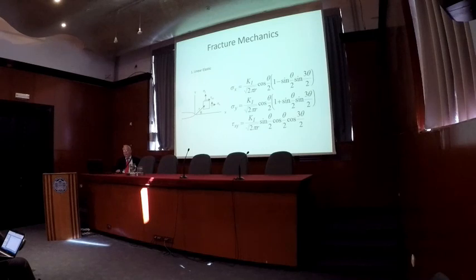The important thing about these is that the distributional terms, where R is the distance from the crack tip to the stress element point, and theta is the angle from the horizontal, are unique. That is, whenever there is a mode one loading, those terms always come up, the same terms. The only difference is in this K. The K is called the crack tip stress intensity factor, and it represents first the magnitude of the field. So these parameters are all field parameters. K is a magnitude, and K also represents the way the loading and the geometry interacts with the crack tip stresses.